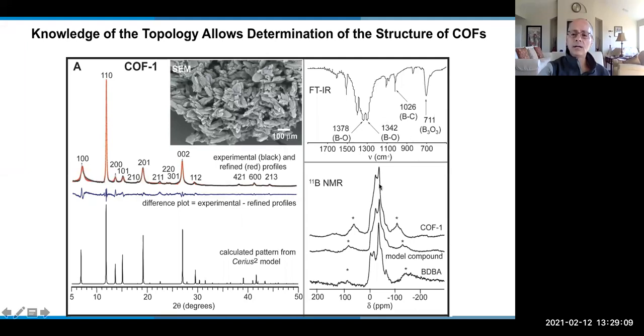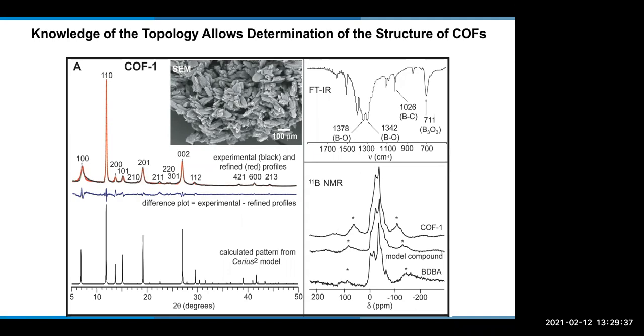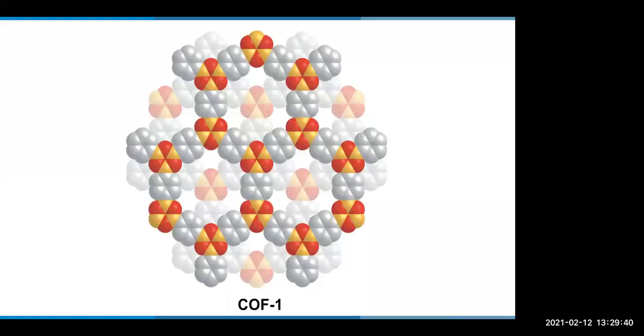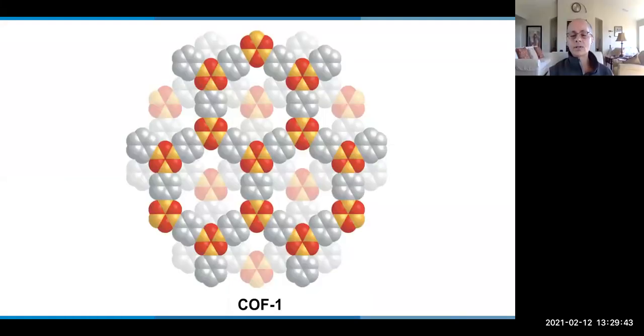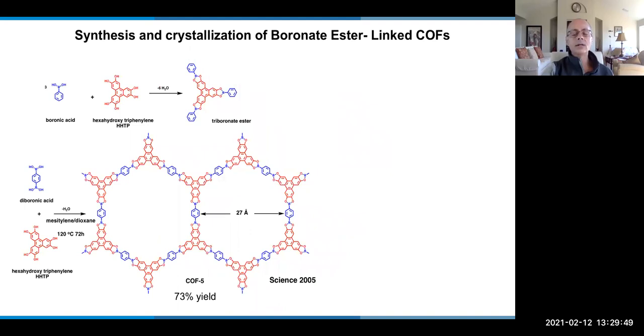I will not mention too much about this in the next set of compounds, but this is the routine protocol for the initial characterization of COFs: you have a sharp X-ray powder diffraction, and you also look at the IR and NMR, in this case boron NMR, in other cases nitrogen or carbon-13 NMR, to assess the completeness of the reaction. So this is the crystal structure obtained from powder diffraction. It's a slipped graphitic layer, a porous structure, and it's the first COF made entirely from covalent bonds between boron, carbon, and oxygen.